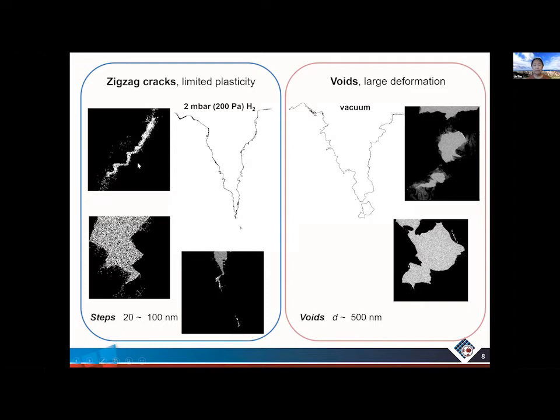Here I show you several images during the deformation process, and in the hydrogen embrittlement case, we see zigzag cracks, or this rectangular staircase-like shape of the crack. If we see the 2 sides of the profile of the fracture surface, they almost overlap with each other, indicating the plasticity is really limited. This is not happening in the case where we test the sample in vacuum. Here we see pretty large deformation in the material.